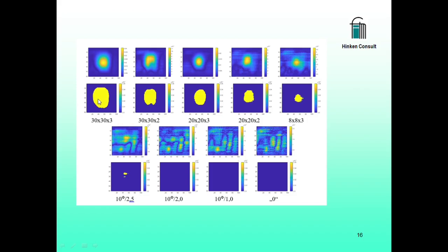and the lower lines show yellow areas in which the amplitudes are above a threshold level, which is given by the noise. The noise is the residual noise from the inhomogeneous balsa wood, which could not be eliminated by the lens principle. However, most of the balsa noise was eliminated by using the lens.